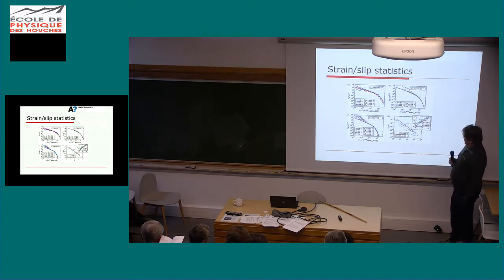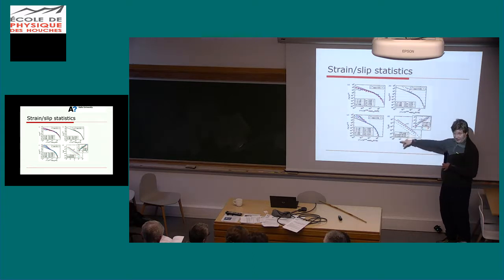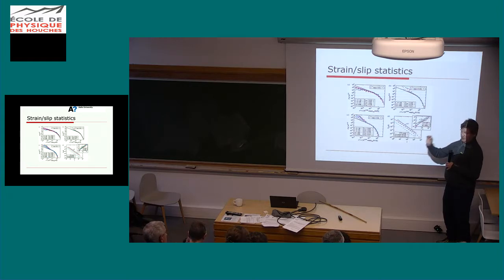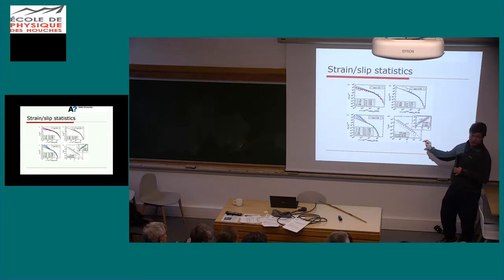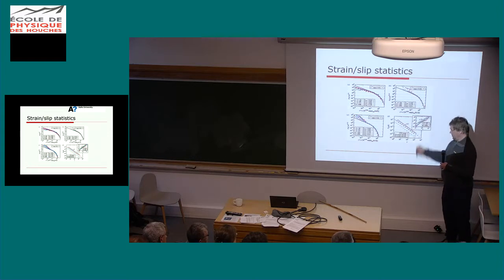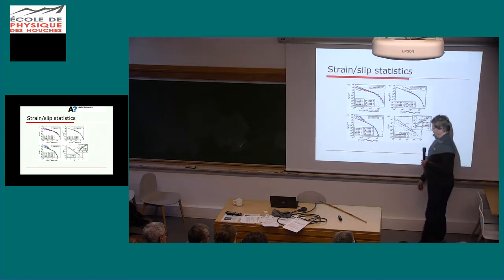This was tested in various contexts, like, for instance, what's the precise model and how many dislocations you put in the system. And why this is important: this tells you that you can make a coarse-graining step. You can either follow directly the dynamics of dislocations, whether they go slowly or fast during an avalanche, or you can do a cellular automaton, saying that either it moves or it doesn't, the velocity is the same. Still you get the same kind of integrated avalanche size distributions.